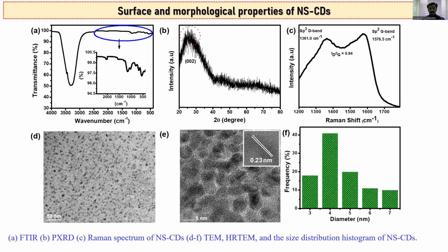Then, confirmed from XRD, this carbon dot exhibits a broad XRD 2 theta peak around 25.5 degree, which is attributed to the 002 plane of graphitic carbon. We also confirm with Raman analysis from the surface analysis. It shows two major peaks at 1576 and 1361, corresponding to the two different bands, the G band and D band.